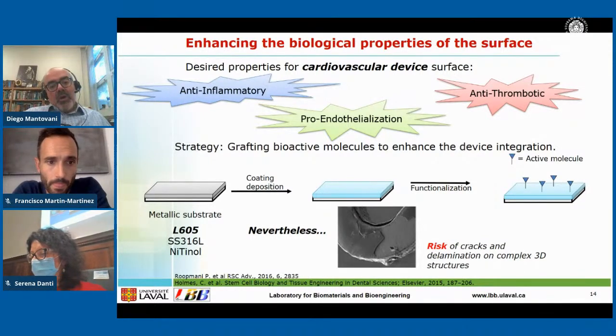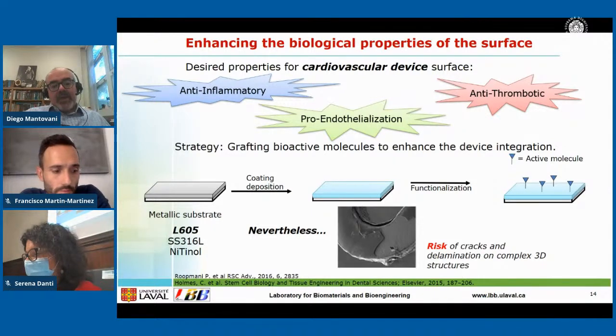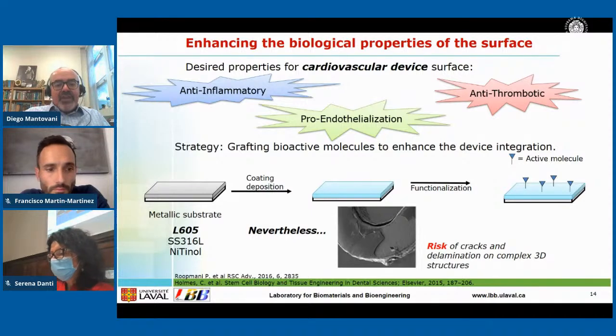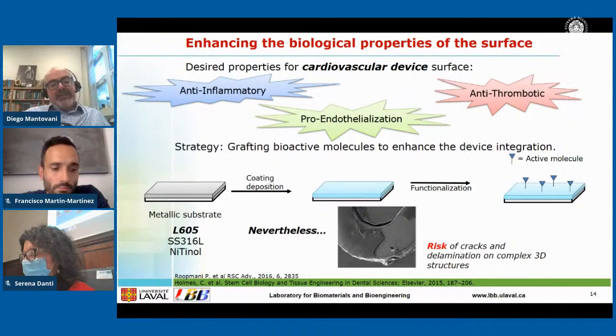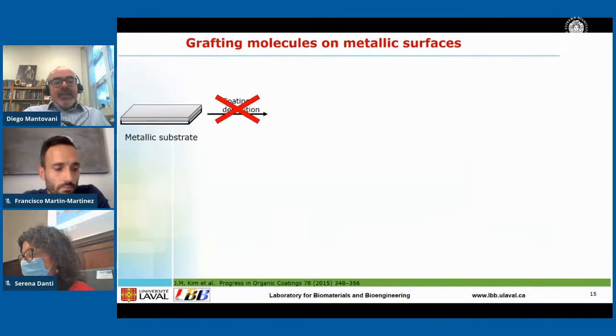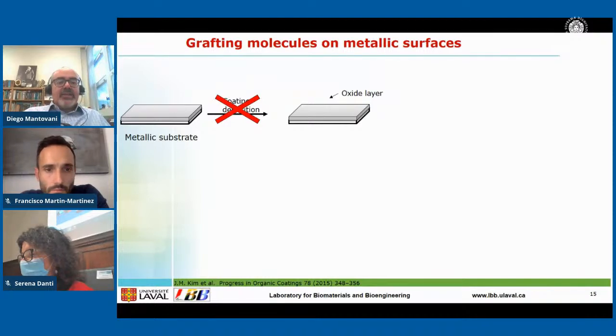In this project, one of the innovative approaches was to challenge the use of a polymeric layer. Abbott, for example, has the Xience stent on the market. This is a stent just coated with a very thin fluorocarbon layer to avoid adhesion and proliferation of smooth muscle cells. In this work, we wanted to bypass this and limit the coating presence. Our challenge was: can we graft a functional group directly, without acid, without liquid, humid chemistry? How can we attach to a metal a molecule, for example a very small peptide, to get a strong binding that resists deployment in the body?